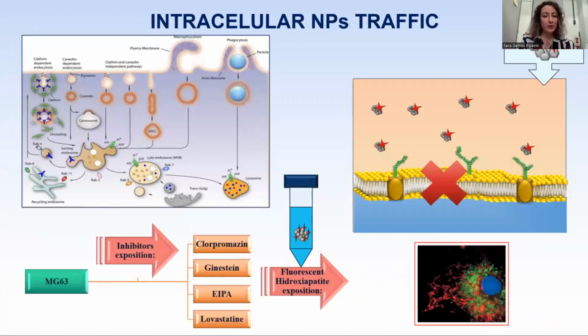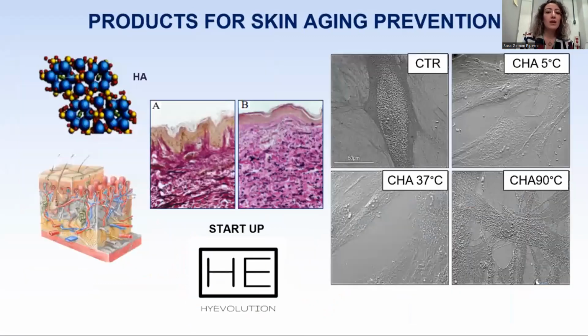So these results open the door to new questions that are still being investigated in the lab, such as how these nanostructured materials are internalized and processed by bone cells, and how this influences the biological effect on the cells. This question will be answered using hydroxyapatite conjugated with rhodamine, that is fluorescent hydroxyapatite, together with specific internalization pathway inhibitors and a lysosome tracker. Moreover, hydroxyapatite is a material that is used as a biomaterial in fillers for skin aging prevention. So in collaboration with a startup called Hyevolution, we are testing the carbonated hydroxyapatite that we synthesized at different temperatures, putting it in contact with primary fibroblast culture to evaluate the biostimulator potential of our materials in fibroblasts.